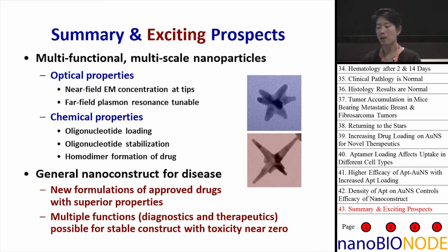But then what people found in terms of in vivo work, so not for cell work, but for in vivo work, you wanted them close to neutral, because if they were too negatively charged, they would be just taken up by macrophages. This is what we found too, is bad. But if it's too positively charged, then you introduce all of these cytotoxic effects that were sort of unknown.